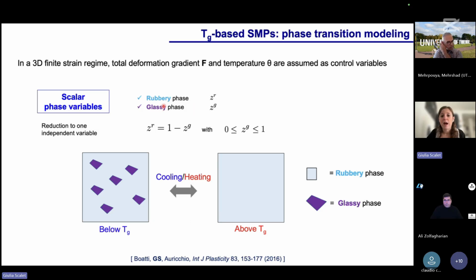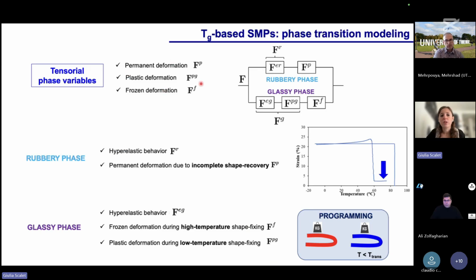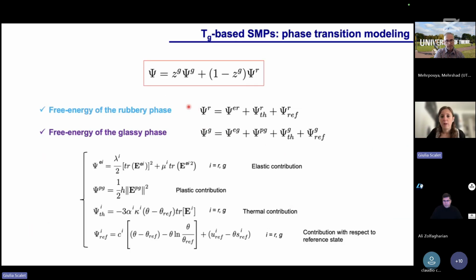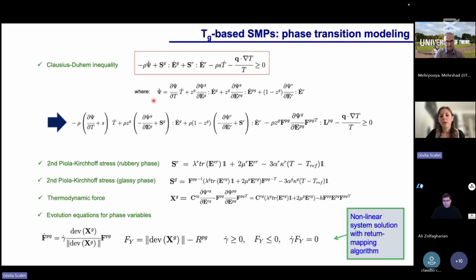In this case, we have a rubbery and a glassy phase, since the polymer is based on a glass transition, and you can introduce a specific tensorial phase variable to describe all the inelastic deformation that are associated to the different shape memory effects. And you can obtain a model, in this case, that is able to describe different effects, not only the basic one, but also an incomplete shape memory behavior. So you can define the Helmholtz free energy as classically done in the literature with a mixture of rules, and you can derive in a thermodynamically consistent framework all the constitutive equations. So you can implement into numerical code.